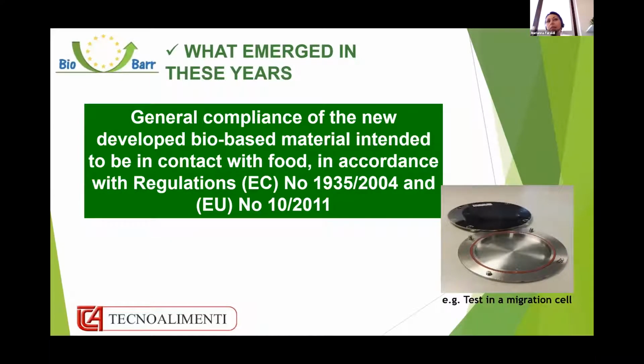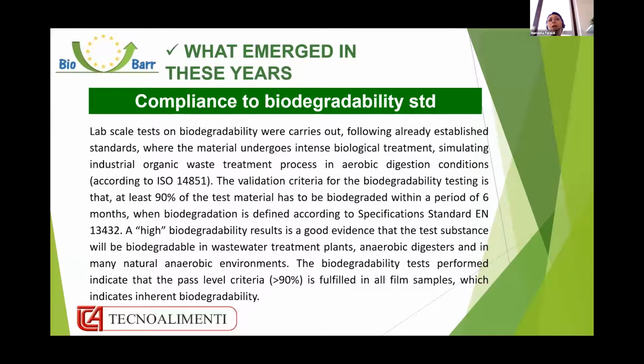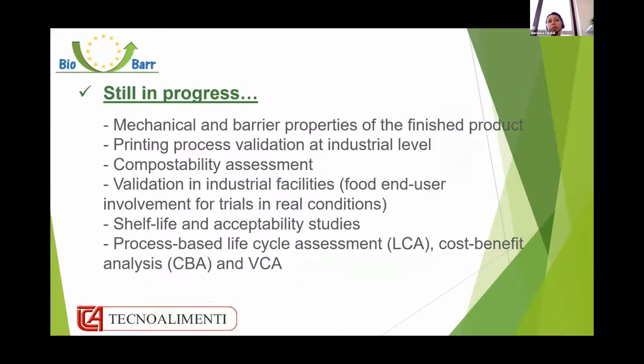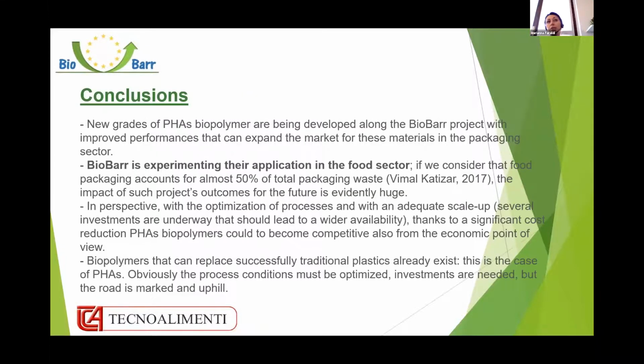And in terms of analysis, we can confirm at the moment the general compliance of the new developed bio-based material in contact with food. So we have tested the overall and specific migration, compliance to biodegradability standards, but still in progress, the compostability assessment, some evaluations in terms of mechanical and barrier properties of the finished product, the printing process validation at industrial level, and the shelf life and acceptability studies, and LCA, CBA, and the value chain analysis.